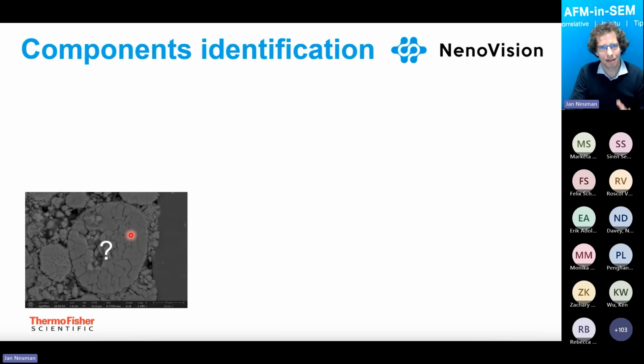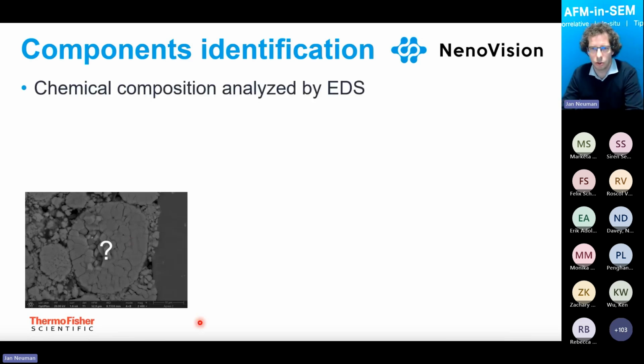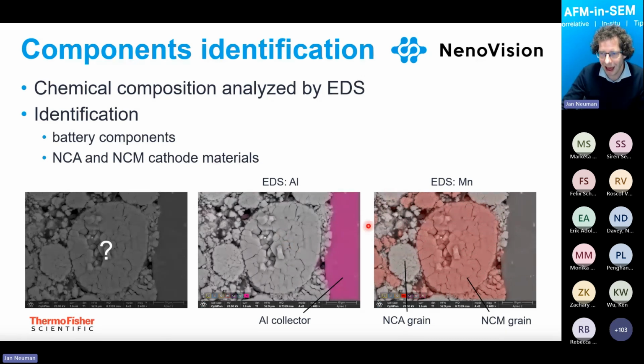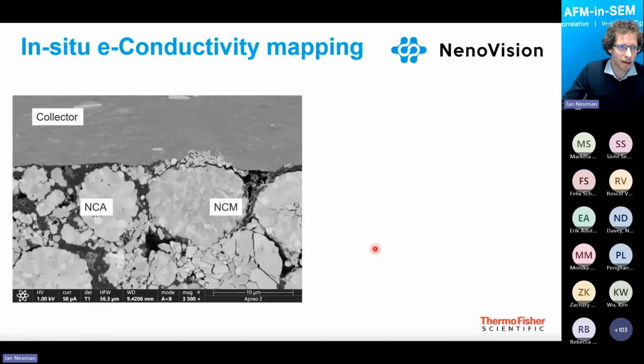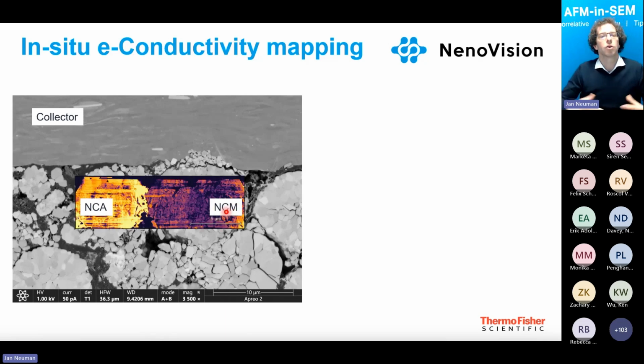So, the component identification again. This is a picture which you see in the SEM. We use EDS to analyze different elements. With aluminum, we immediately visualize the collector. And using the manganese composition in this case, we can distinguish nicely between the NCM and NCA grains of cathode materials. Taking that, we can directly say on such a picture that this is a collector, this is an NCM particle, an NCA particle, this is an NCM particle, and we can continue with the conductive mapping.